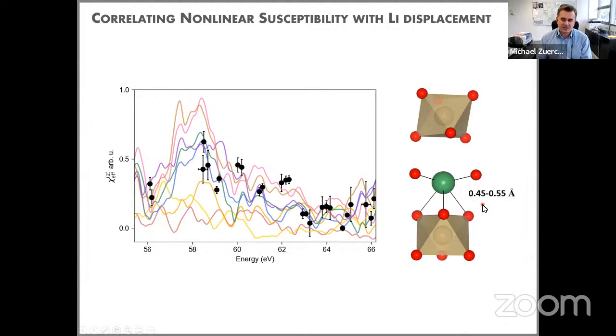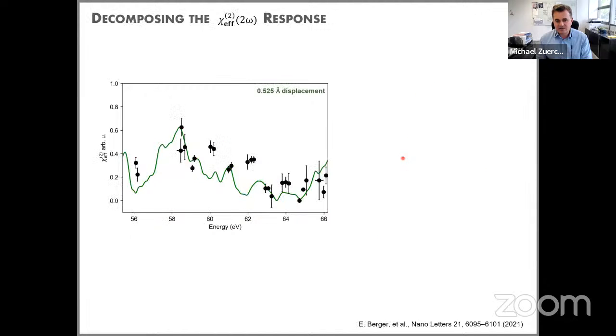And this is quite nice because the other number we had from literature was done with neutron scattering. With this neutron scattering, I think they observed 0.5 angstroms. So we are spot on with our estimate of the lithium displacement. But now this is done with X-rays, with femtosecond X-rays. So we can now in the future think about doing time-resolved measurements, which is something you cannot do with neutron scattering. Plus X-rays are generally much more accessible than neutron sources. So that was a very nice first result.